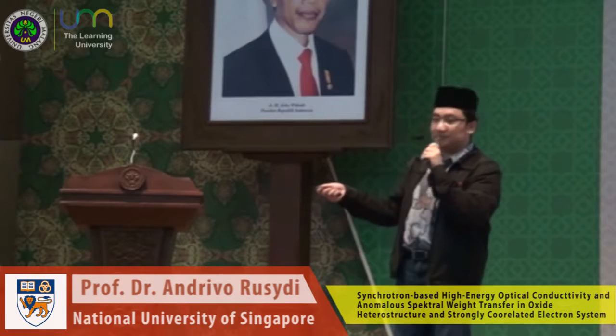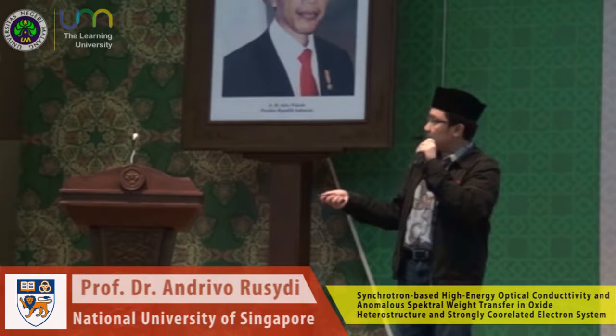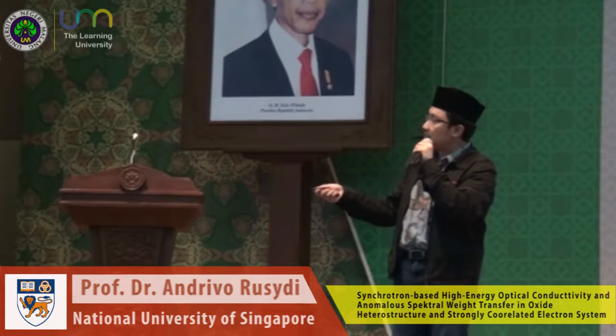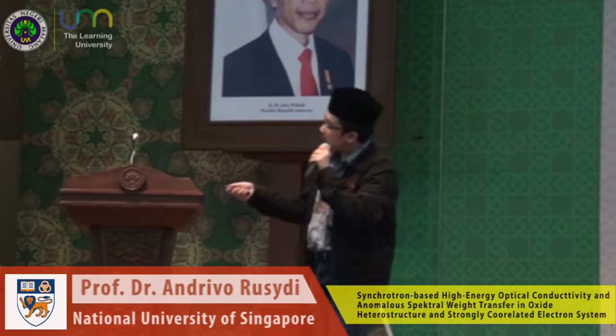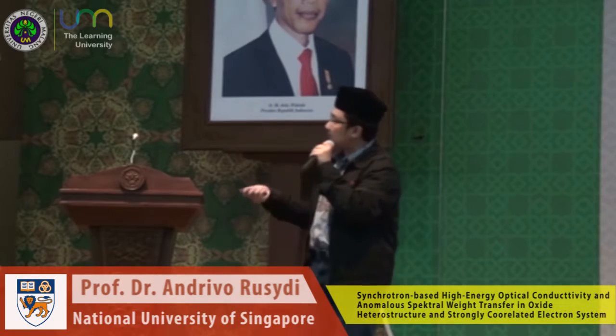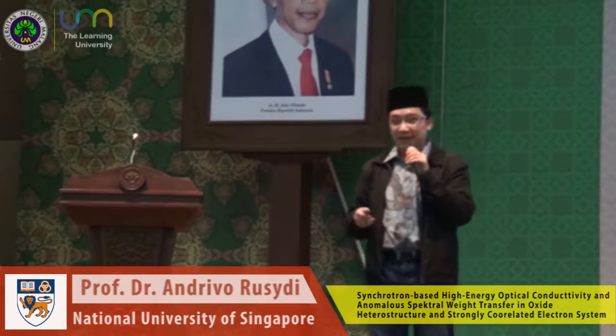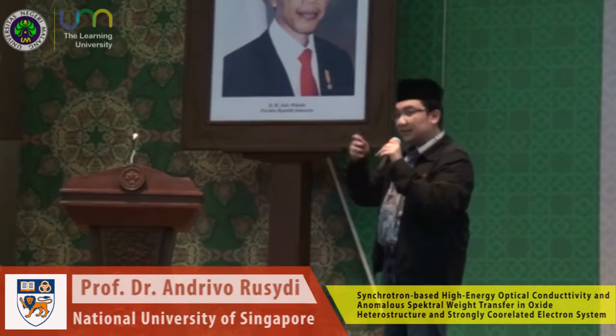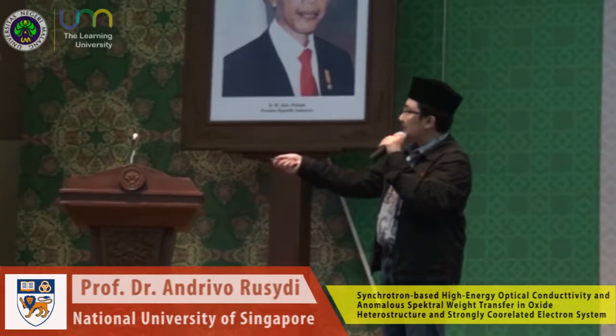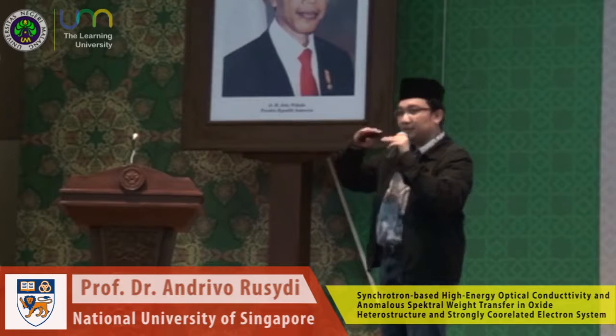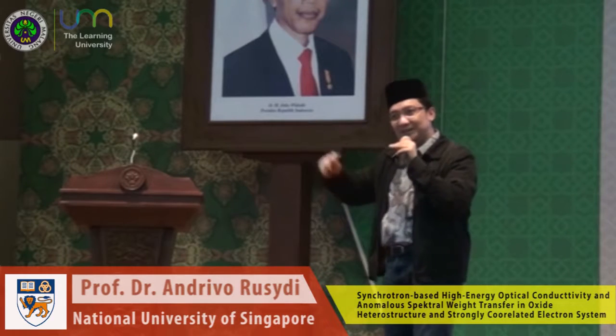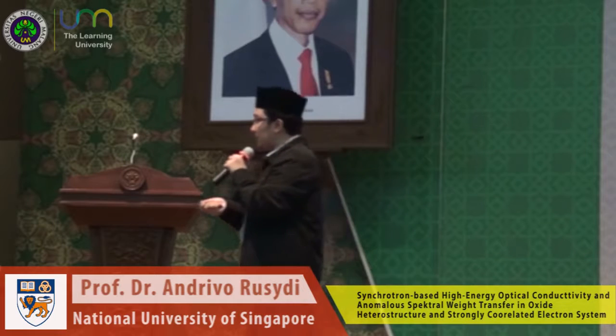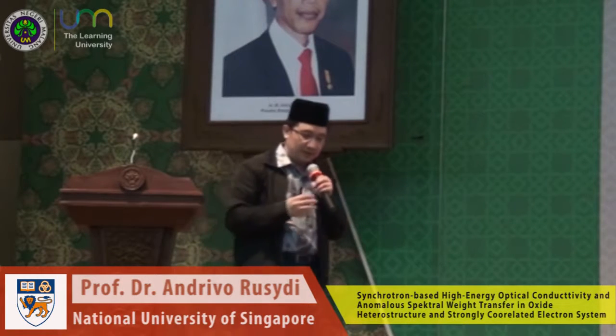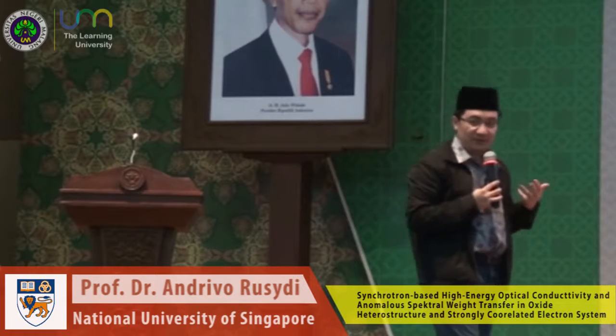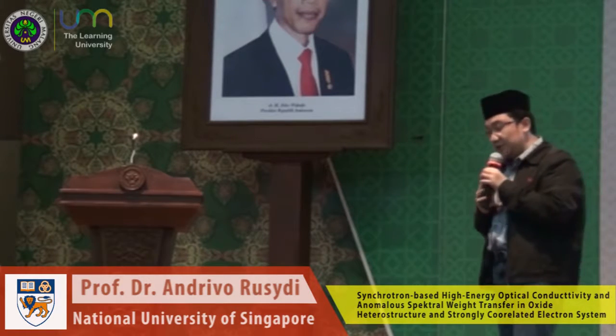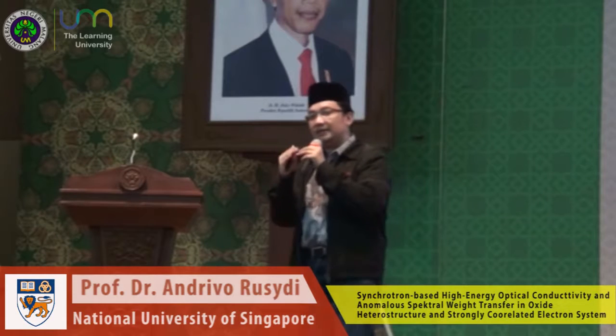But check what happened when you add another unit cell of LAO. The conductivity jumps up tremendously, from zero to something. This is 2 times 10 to the 13 electrons per square centimeter. When they increase the number of unit cells to 16, the conductivity remains flat, almost the same. This fascinating phenomenon, discovered around 2004, was a big hit in the oxide community, because we think of new materials for new energies, or even new devices, because things happen at interfaces.